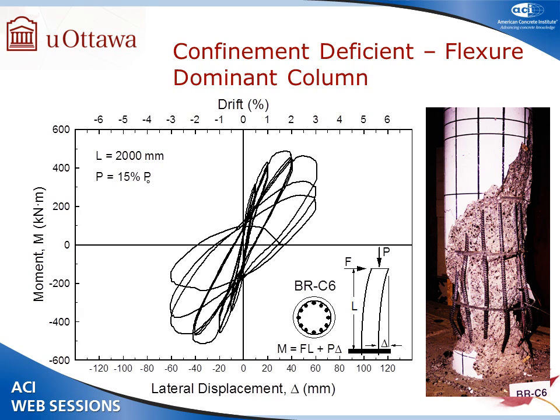Then we looked at flexure dominant columns where essentially failure mode was lack of confinement. These are again hoops spaced at 1 foot spacing, intentionally under-designed. And this time, due to the inherent ductility of reinforced concrete, even without confinement, we were able to go up to 2% drift, and then it started decaying. I have to reemphasize the fact that these are bridge columns under low levels of axial load. Under higher levels of axial load for building columns, you may not get 2% drift.